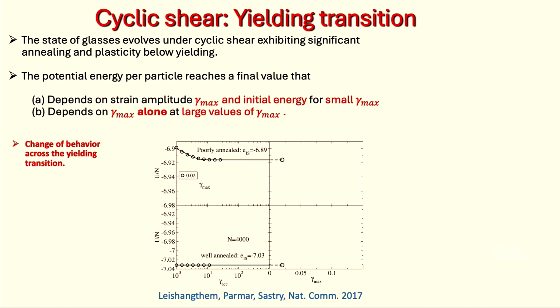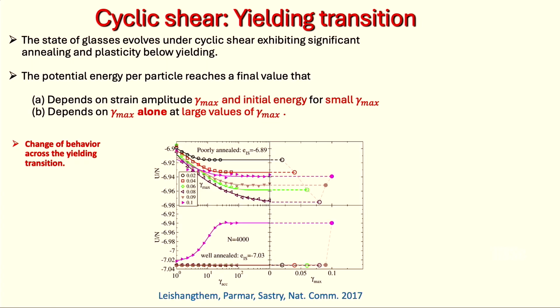So this is a small amplitude shear, cycle to cycle, the energy changes and reaches some final value. A larger amplitude will lead to a lower energy being reached, and it takes longer to reach that. And one keeps going till beyond some amplitude of shear, there's a qualitative change in behavior where the energy now begins to go up. In this part of the story, depending on whether I start with a poorly annealed glass or a well annealed glass, the behavior is very different. But if I go to larger amplitudes, now I begin to have final states, it's not very obvious from this picture, which don't depend on whether I started with a well annealed glass or a poorly annealed glass, but I reach the same final state.